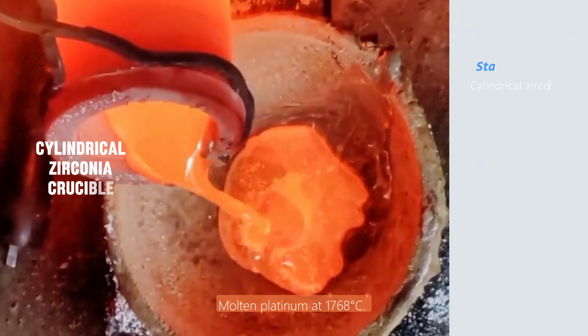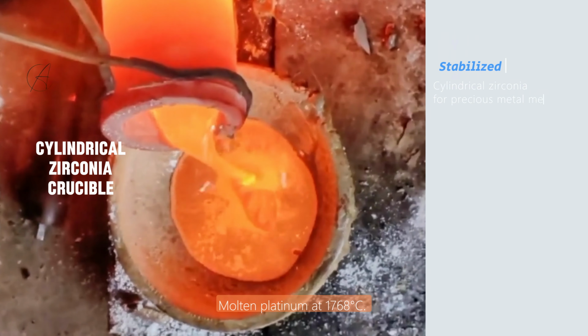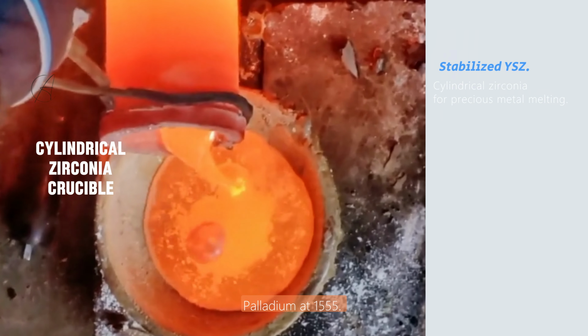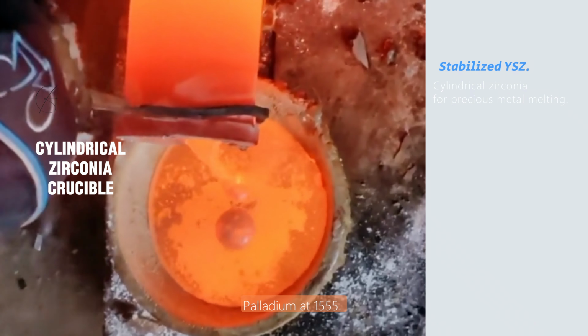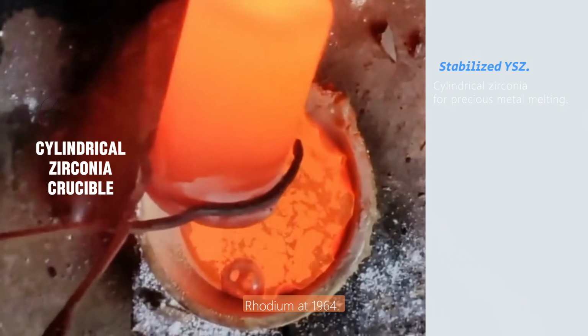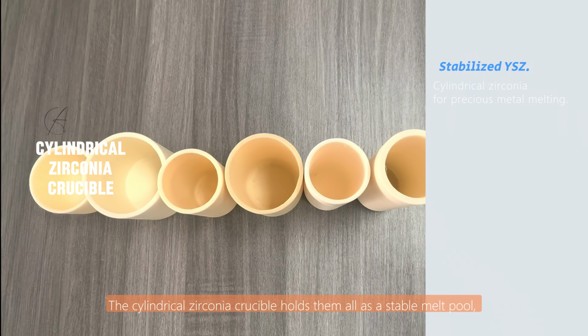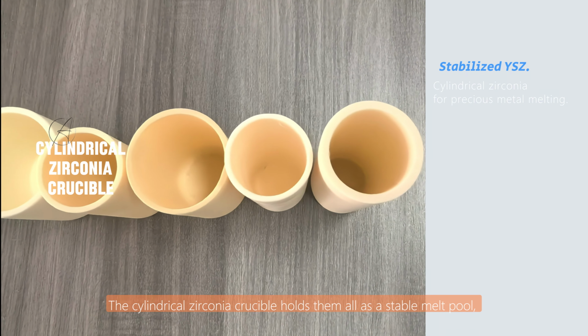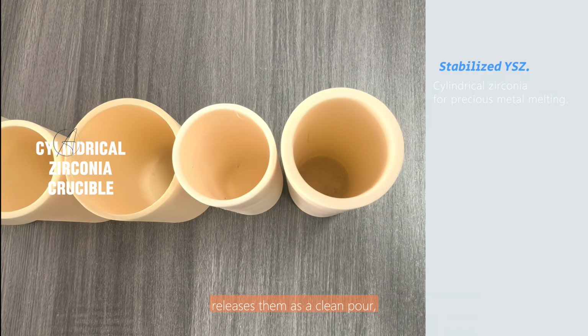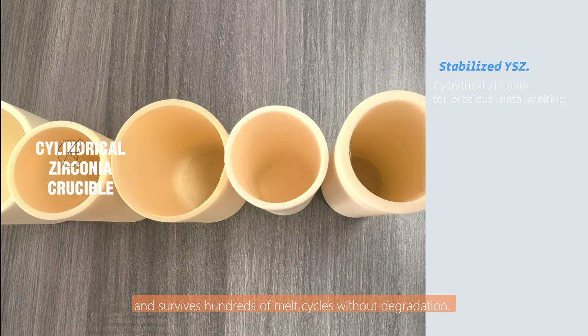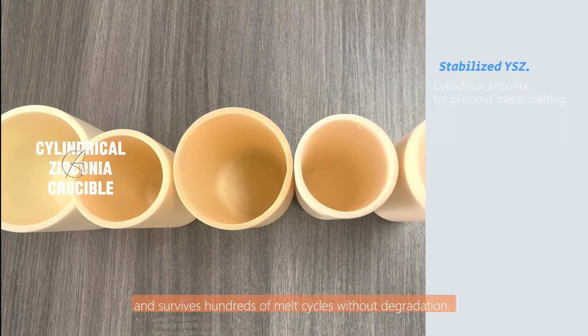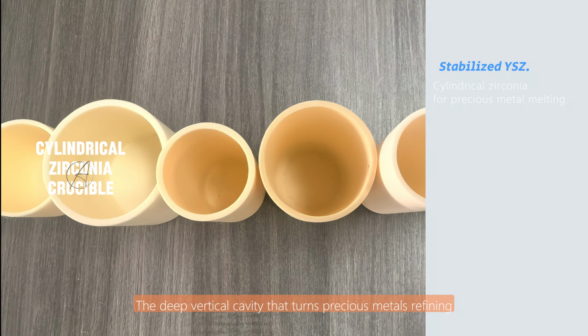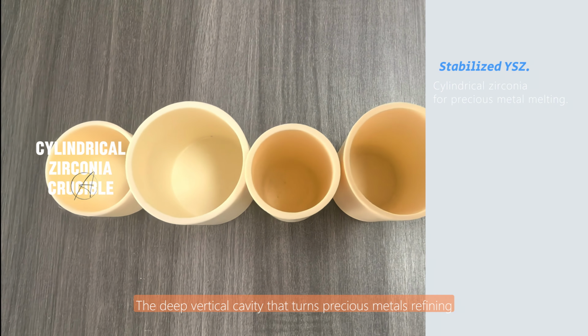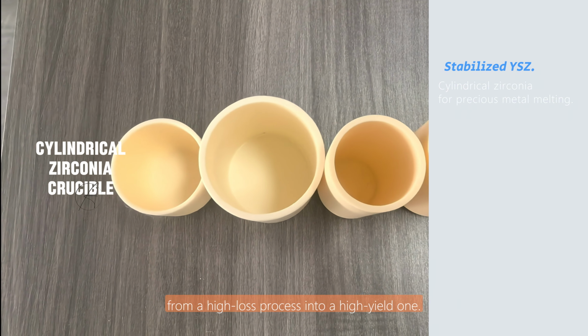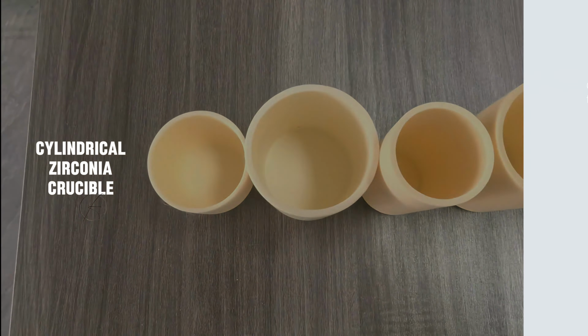Molten platinum at 1768 degrees Celsius, palladium at 1555, rhodium at 1964. The cylindrical zirconia crucible holds them all as a stable melt pool, releases them as a clean pour, and survives hundreds of melt cycles without degradation. The deep vertical cavity that turns precious metals refining from a high-loss process into a high-yield one.